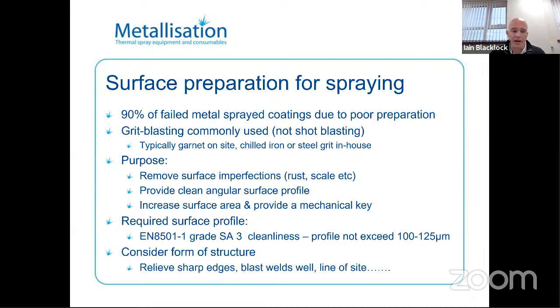The other thing to consider is the form of the structure. So if you've got sharp edges, blast welds, you want to concentrate on those areas. So break the edges just so you haven't got stress risers. Give good blasting onto the weld areas, which are notoriously the most difficult to get the profile on.